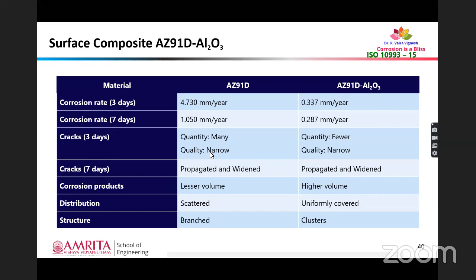And when we analyzed the surface morphology, the cracks were many and narrow after 3 days of immersion in the base material, and in the composite they were few and narrow. After 7 days there is obviously propagation and widening of the cracks, and that is all because of the corrosion reaction that is taking place in the material.